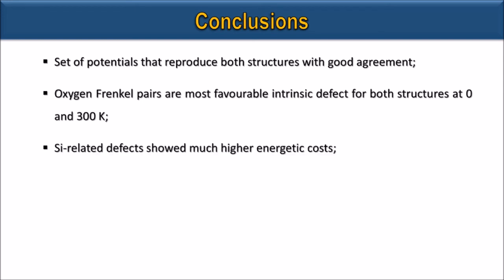These results can be used to support the interpretation of the intrinsic luminescence found in these materials, which is supposed to be due to self-trapped excitons stabilized by oxygen ions not bonded to silicon species. And that was exactly what was found for both structures, where the oxygen interstitials stabilized by the oxygen vacancy counterpart in the oxygen Frenkel defects are disconnected from the silicon polyhedra.